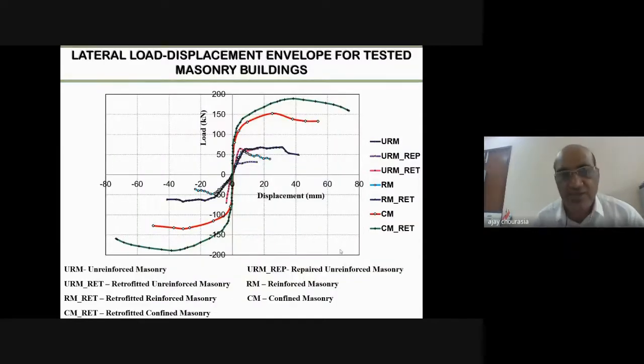And again, from the engineering perspective, for a better understanding of the test results, you need to draw the typically observed hysteresis loop followed by the load displacement curve. In this slide, you can see the load displacement curve for all the tested masonry walls along with the retrofitted confined masonry, CM RET. Interestingly, earlier we observed around 152 kilonewton peak lateral load resistance and 54 mm maximum displacement. In contrast, the damaged confined masonry model after retrofitting has further enhanced the lateral strength to around 192 kilonewton, and deformation up to 74 mm.